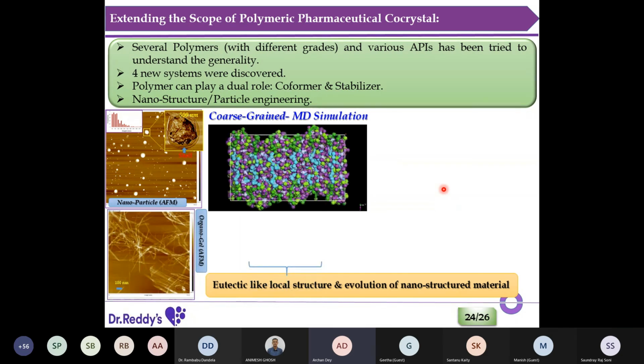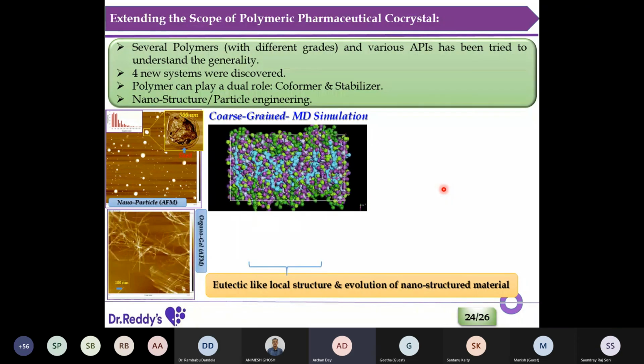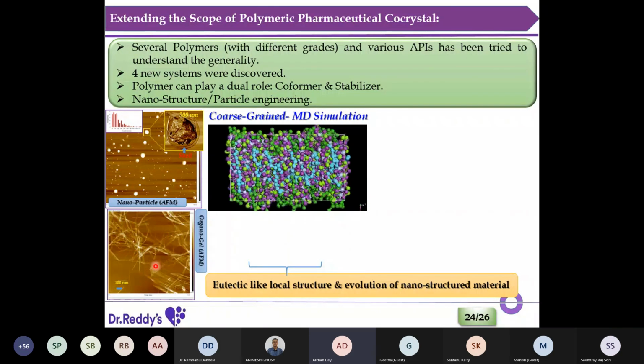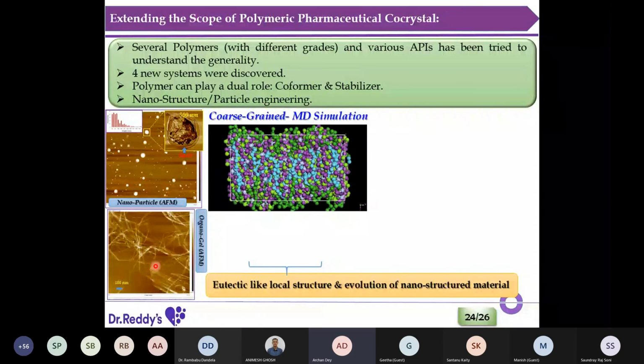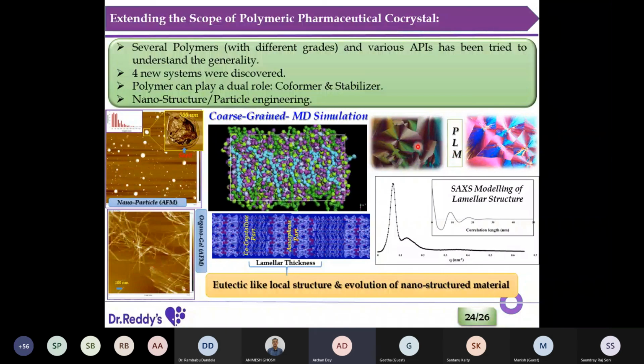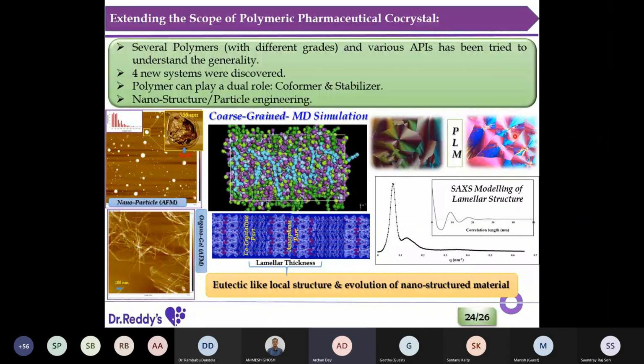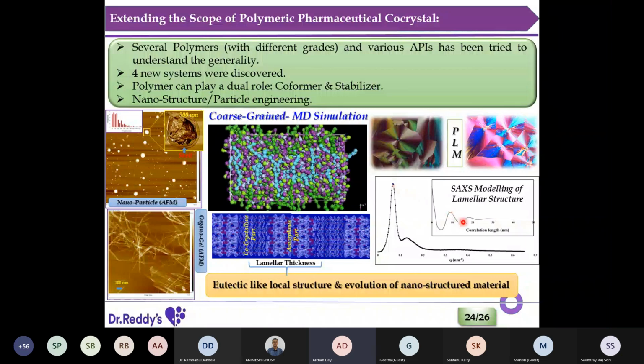Okay, and also if we put this type of material in an organic solvent, we start to get organogels. That's another way to control the drug delivery. You can see the nice PLM images of this liquid crystalline material, because that means they have a lamellar structure. That lamellar structure we can model with small angle scattering data, and we can find out the lamellar thickness of the co-crystal parts and the amorphous part. In principle, nowadays we are working to develop a coarse-grain molecular simulation to understand the eutectic-like local structures and evolution of such nanostructured materials.